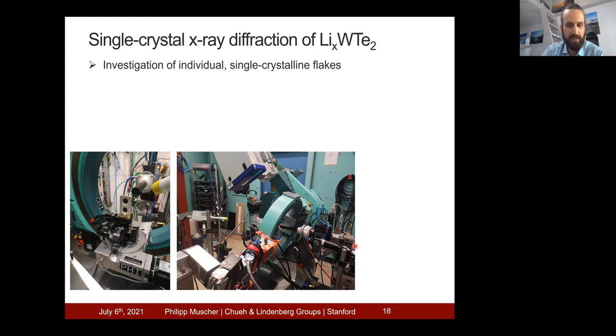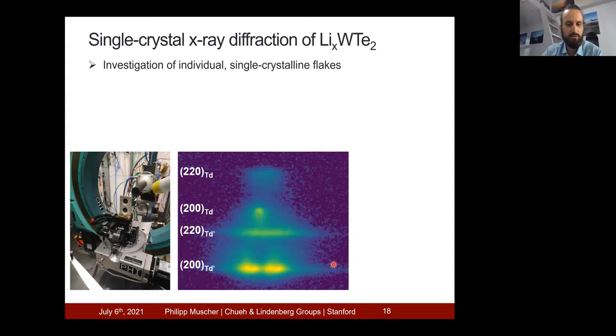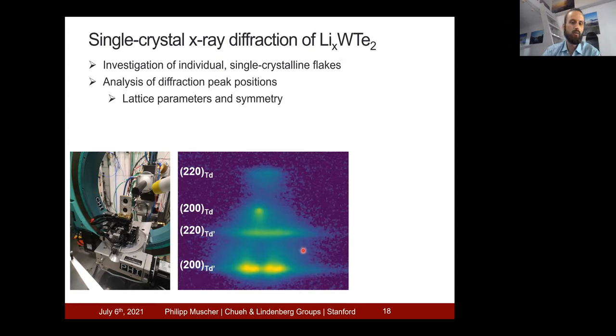Here's the side view of the system. So the X-rays come out of this tube, hit the sample, which is hidden over here, and then these X-rays diffract off our sample, so they get scattered, and we have this detector which captures the scattering, so this diffraction pattern. An example of such a diffraction pattern is shown over here. By analyzing where the peaks are in this diffraction pattern, we can learn about the lattice parameters and the symmetry of the material that's being studied. But we can also look at the peak intensities, and from these, we can learn where exactly in the unit cell our atoms are located.